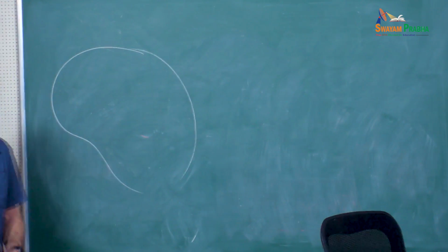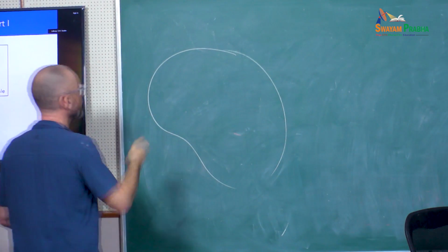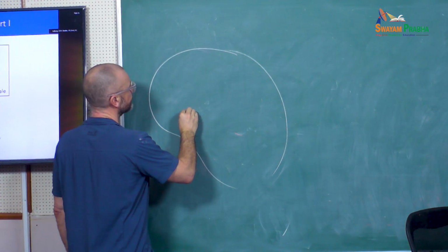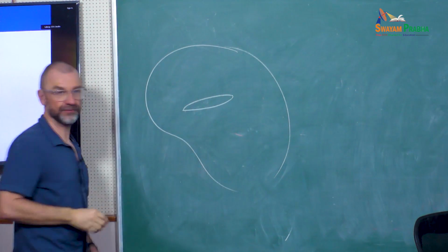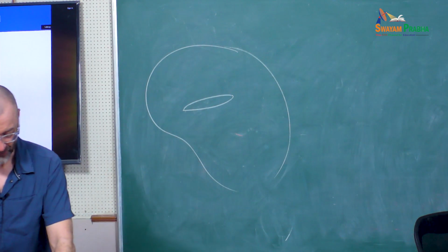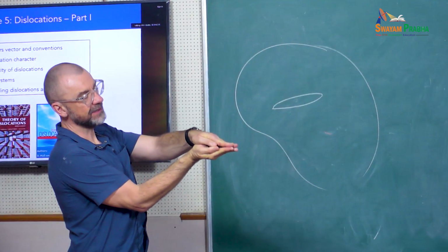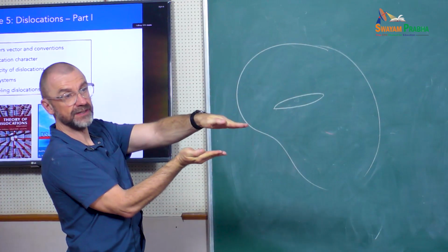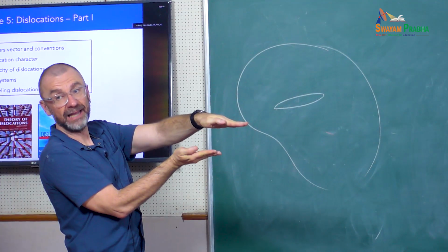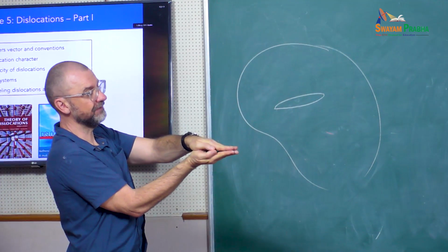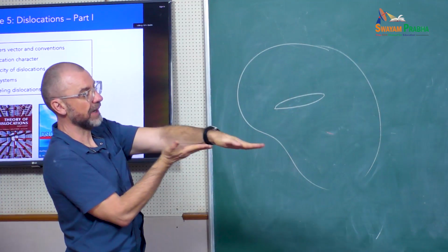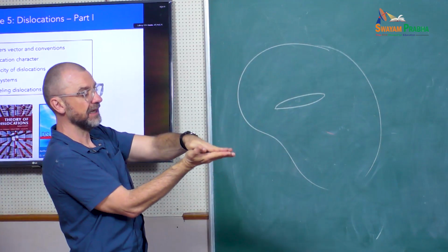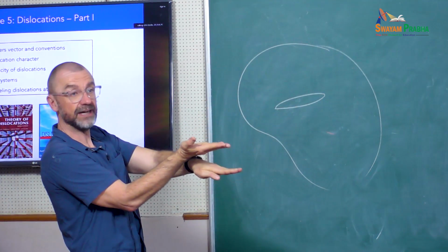and then you take a magic knife, you go into your body, and with your magic knife, you make a cut along a surface. So you have created a surface inside your material. Then you displace the two surfaces by a given vector. That vector can be parallel to the surface, perpendicular, or in any direction. It can even go inside.